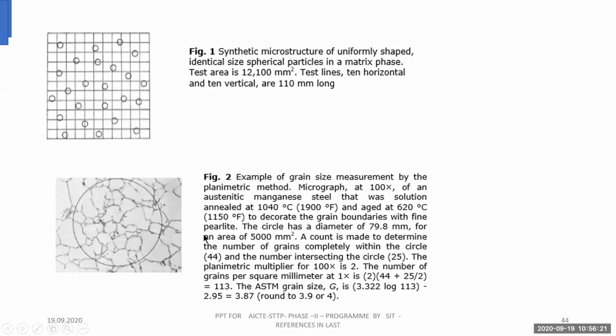As already explained for the rectangle, here it is a circle. Within the circle, the example of grain size measurement by the planimetric method: micrograph at 100x magnification of austenitic manganese steel that was solution annealed at 1040 degrees Celsius. So annealing was done, and then an aging process at 620 degrees to decorate the grain boundaries with fine pearlite. So there is austenite annealing and aging and formation of fine pearlite, and after that they tested. The circle has a diameter, this is standard size 79.8 mm.